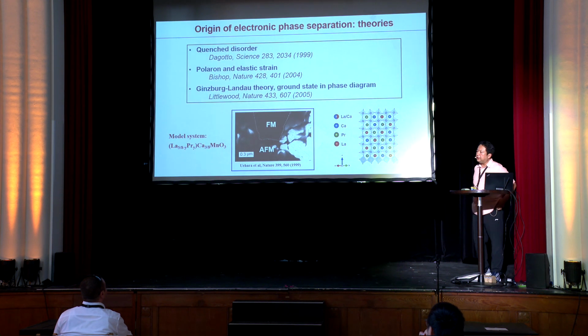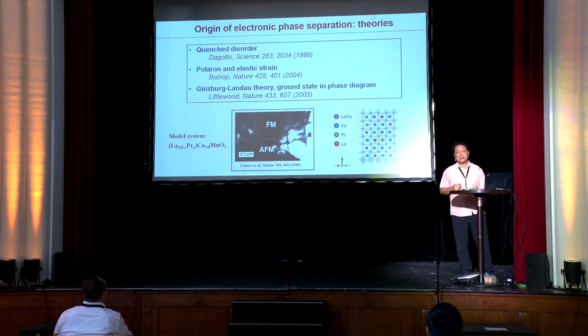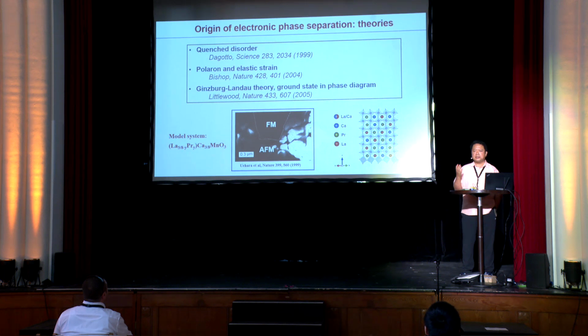In fact, if you are serious about first-principles calculations, then you already start to wonder that this is indeed a very strange phenomenon. If you have a single crystal, then the coexistence of antiferromagnetic and ferromagnetic states as a ground state is very strange, because usually, energy-wise, one of the states has to have the lowest energy. How come the coexisting phases is the lowest energy state? So that's why there are many theories discussing it from various aspects, but under certain models.